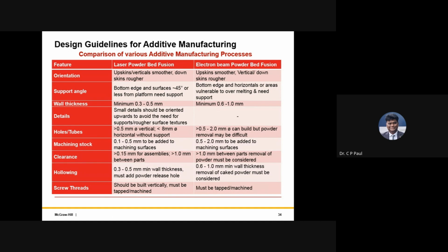Now, when we talk of powder bed fusion systems, specifically with metal additive manufacturing, the two types of technology available are laser powder bed fusion as well as electron beam powder bed fusion. Now you see how these two technologies compare in terms of orientation: you have upskin vertical smoother, downskin rougher, and similar for electron beam. The difference specifically comes when we talk of wall thickness. In laser powder bed fusion, you can have a minimum wall thickness in the range of 0.3 to 0.5, but in electron beam, you have to go to 0.6 to 1 millimeter.